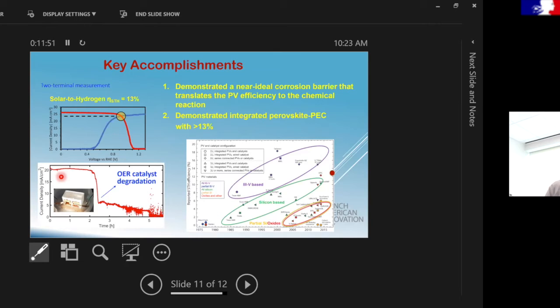So finally, what I would like to do is, I think this is something that we are very excited about. We've now taken this material, and these are typically water-soluble materials, right? You put them in and they dissolve in water. But we've developed a technology where we can create a barrier on these water-dissolvable materials such that it is transparent to the charge, which can go through, but it's completely impermeable to the strong electrolytes, which means that it does not degrade your perovskite at all. And we can drive bias-free autonomous water splitting to generate hydrogen at greater than 13%.